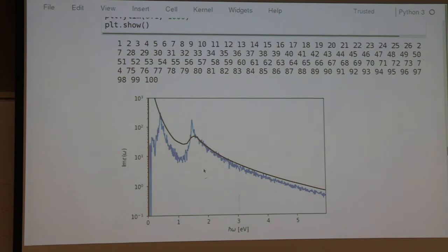Right? And remember that although I didn't show you how we did it, the calculation of the Wannier Hamiltonian and so on you've been using doesn't have any experimental input, right? It's purely from saying that this is my crystal structure, these are where my atoms are, these are the charges on the nuclei, solve the Schrodinger equation for the electrons, and we're starting just from those laws of physics and predicting this experimentally measurable quantity, right? Now, it agrees really well in this energy range, but we are overestimating the experimental result here and then underestimating it here, completely not capturing this blowing up to infinity. Right? So now why is that?